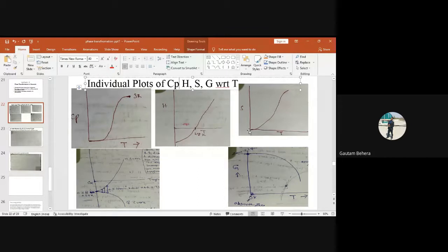So you have to remember, whenever we are dealing with a pure metal or pure element, then we have only thermal entropy. But the moment we are dealing with an alloy or a metal with impurity, or a system having two components, then we have two kinds of entropy, thermal as well as configurational.